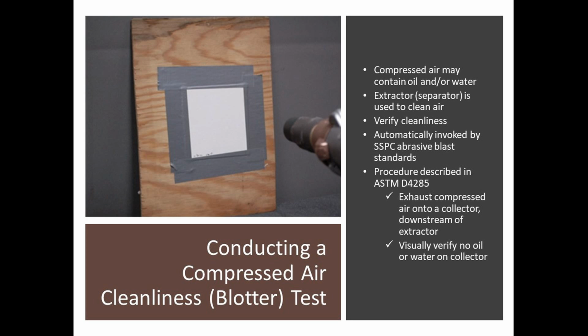There's the potential that the compressed air will have water and maybe even oil contamination in it. We need to make sure the extractors or the separators that are in line are doing their job, removing those materials before we exhaust the compressed air on the surface or combine it with the abrasive. Once again, even if your specification doesn't specifically require this test, the SSPC and NACE surface cleanliness standards require the use of clean, dry, compressed air. How do you determine that? You do a test like this. Simply exhausting the compressed air for about a minute onto a collector and examining that collector for oil and water is all you do essentially.